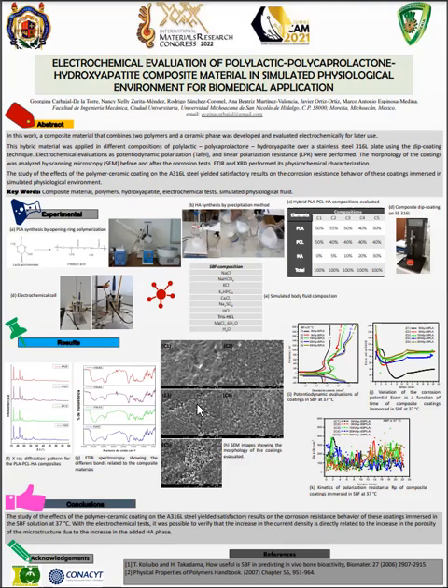The morphologies of the different coatings are observable in Figure H. Here, we can identify that the porosity of the microstructure is related to the increase in the added hydroxyapatite phase. The electrochemical reactions in the substrate interface represent a significant activity, and the increase in current density is directly related to the rise in the microstructure porosity because of the increase in the hydroxyapatite added.